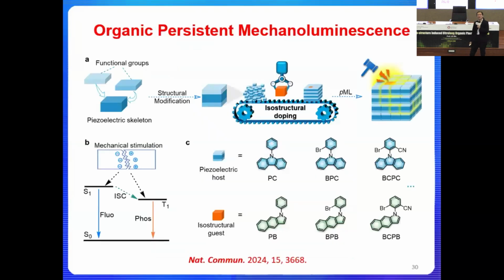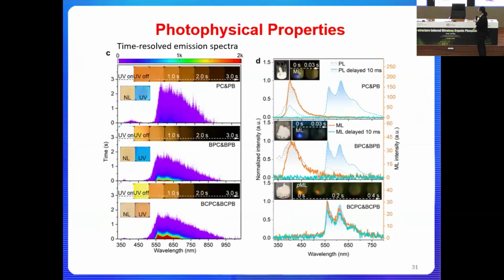So the molecular design is very simple. Just get any mechanoluminescence system that you work with. But we have to purposely introduce isostructural dopants, a very small amount, 0.5%, 1% is sufficient. Then we form these crystals, right? As long as you introduce this small molecule, you're going to change the optical feature of the system that you have.